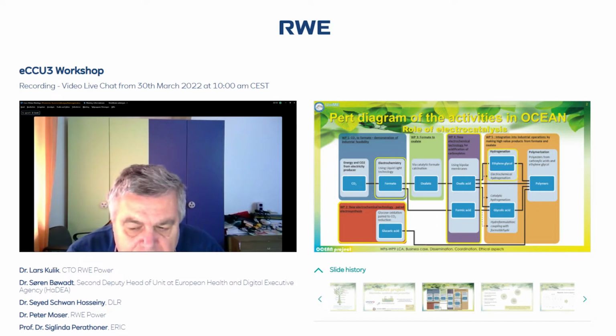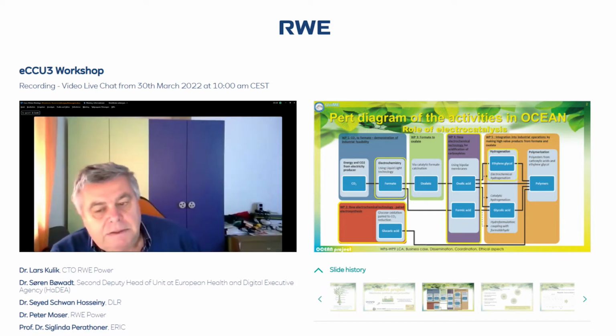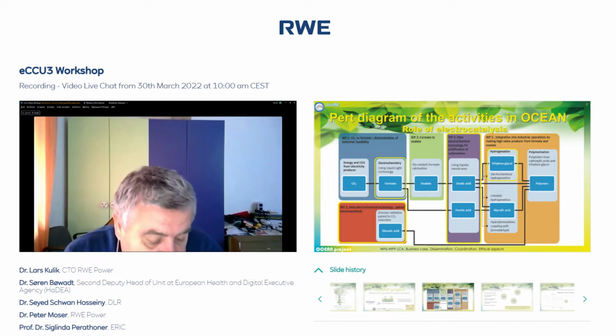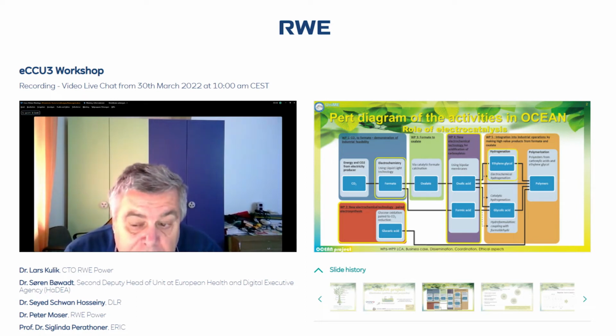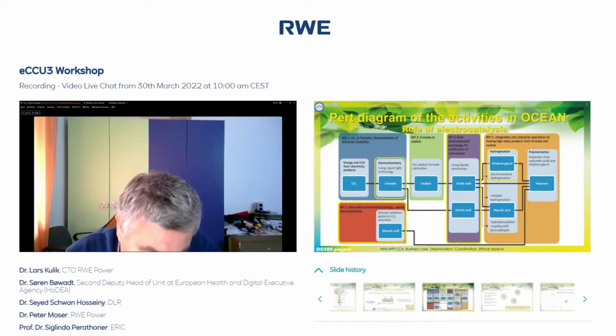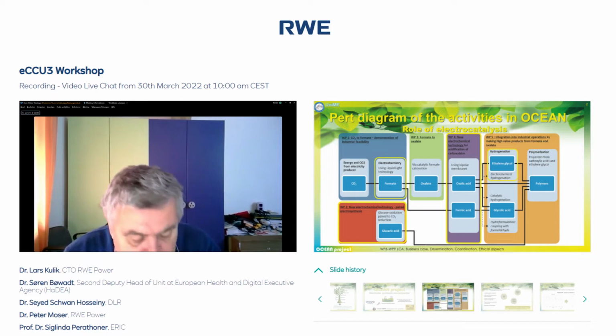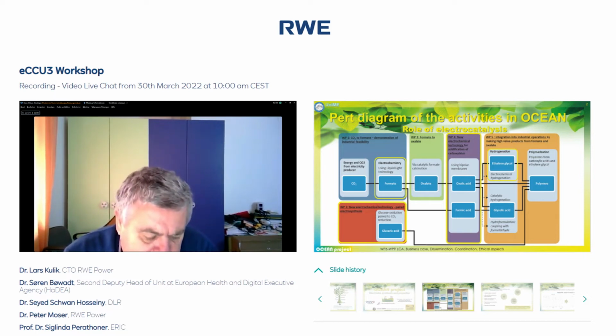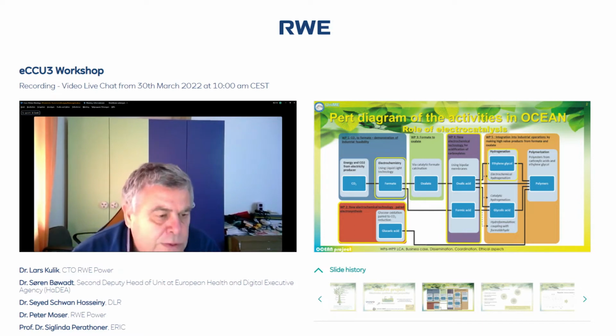And I can say that at the end, we have shown that if you have a good electrocatalyst, and we will see that we have developed some original types of electrocatalyst, then electrocatalytic is an advantage with respect to the gas phase, because essentially what you avoid is all the cost related to putting the reactant in gas phase. You have an aqueous solution, which is relatively diluted. Then, of course, you spend a lot of energy to have gasification of this. And so this is the reason why electrocatalytic hydrogenation has a clear advantage. Besides, the general aspect is that you avoid using hydrogen because you produce it on site from water. And for this reason, you avoid all the side impact related to producing hydrogen.